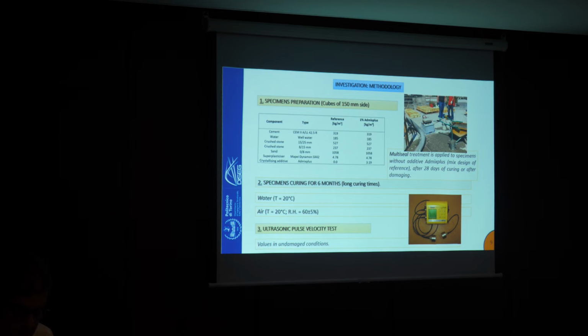But we wanted also to verify if the curing condition affected the self-healing ability. So we cured the specimens for 6 months in two different curing conditions, water and air, which is what you see when you go to a construction site, directly in air. And after these 6 months of curing, we made an ultrasonic pulse velocity test. So in undamaged condition, we in this way had a reference value.